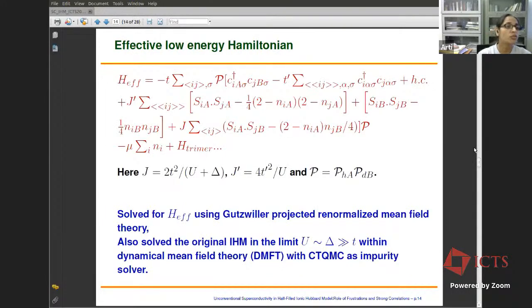So the generalized TIFR transformation on this model at half filling basically gives us this very interesting effective low energy Hamiltonian where we have projected hoppings allowed on the nearest neighbor side, as well as projected hoppings allowed on the second neighbor sides, that is within A sublattice and within B sublattice. We have nearest neighbor spin exchange interaction, and we also have next nearest neighbor spin exchange interaction between the spins on the A sublattices only and the spins on the B sublattices, and then we have many higher order terms, trimer terms, and all which I showed you.